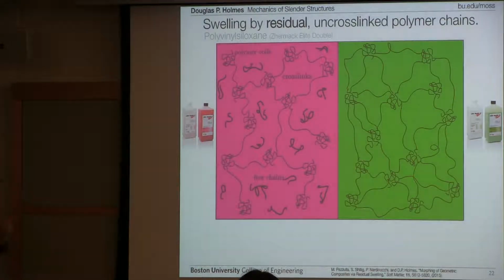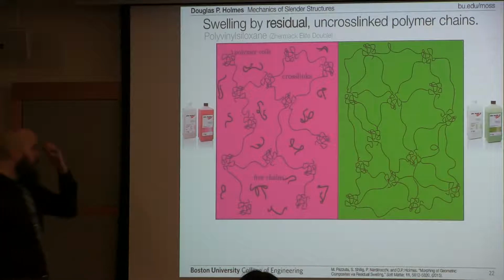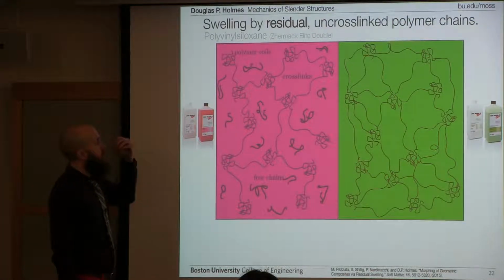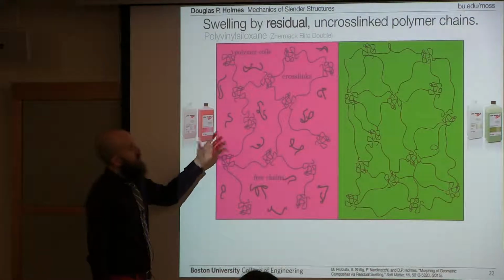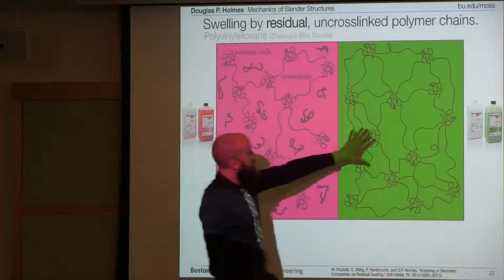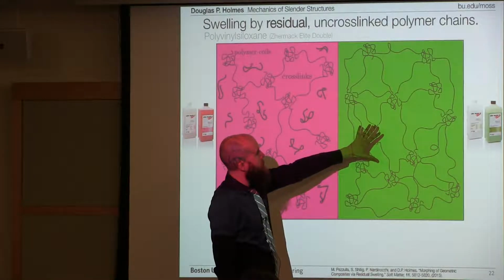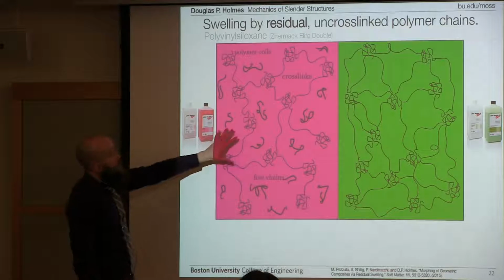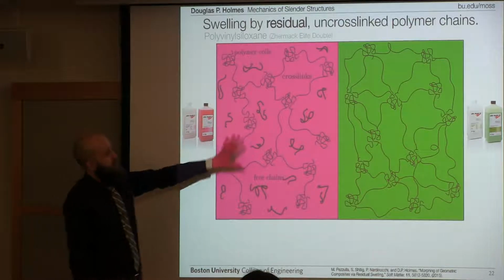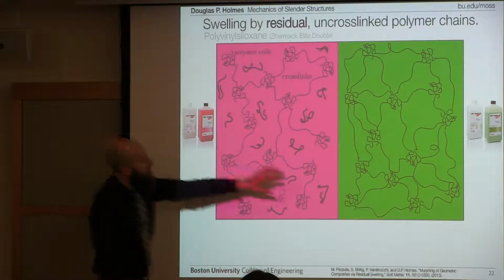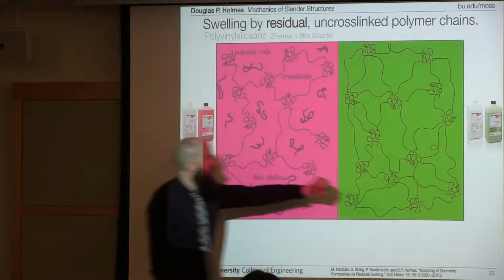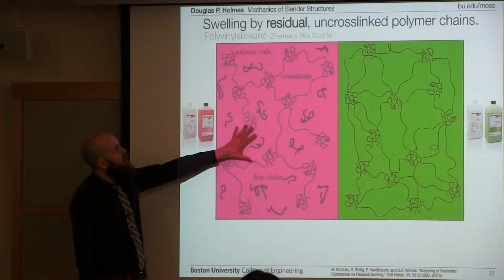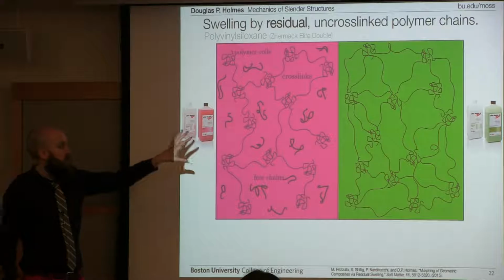So how do we do this? How do we create this in the lab, and how do we study this? Well, in our lab, we developed this technique called residual swelling, where we take a polymer, a cross-linked elastic rubber. We take another polymer that's almost exactly the same, a cross-linked elastic rubber, except this one is completely dry, and this one has some residual uncross-linked polymer chains in it.